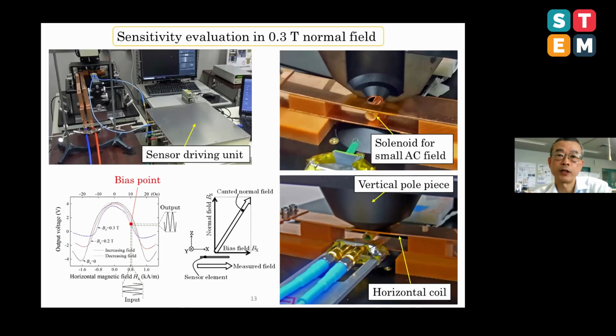This sheet shows an apparatus of sensitivity evaluation. A small alternating field was generated by a solenoid coil in the horizontal direction. This measurement was carried out by applying both a normal field of 0.3 Tesla and the bias field. The magnetic field vector for measurement is shown in the middle. A schematic explanation of this measurement is shown in the lower left figure. The input alternating small field was converted to an output signal at the sensor bias point.